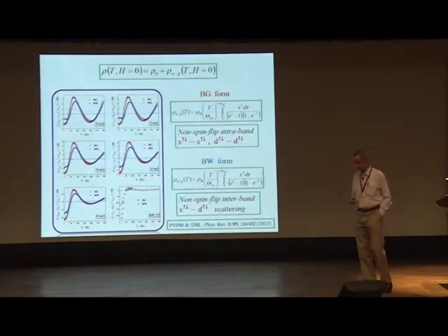Now we go step by step and see how we can identify first which are the dominant scattering mechanisms, and then quantify them in terms of their magnitude. What I am showing you, on this axis, is the percentage deviation, that is, the deviation of the experimental value from the theoretical fit. This is rho experimental minus rho fit, divided by rho experimental, times 100, in percentage.